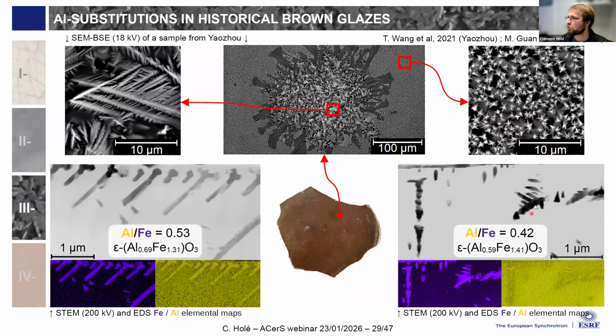And some colleagues from the Palace Museum analyzed in parallel some Jian ware, and they found out on their side that these iron epsilon crystals also contained a high proportion of aluminum inside, showing that aluminum is indeed helping the phase to be stabilized.